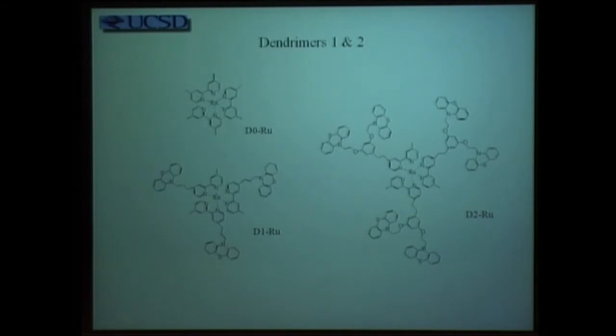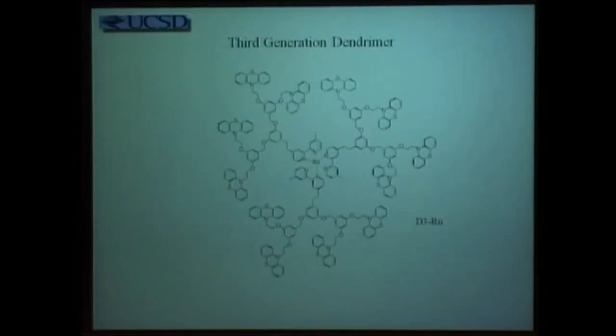Whereas here we have this same rubipy core and 6 absorption units. In other words, what you can do is have stronger absorption by having multiple chromophores located at defined distances around a central core. And there's been a great deal of theoretical interest in how the chromophores interact in this very highly constrained facet. For example, if you look at one more unit in this series, here again is the rubipy, completely covered by substrates of this sort, the third generation dendrimer.